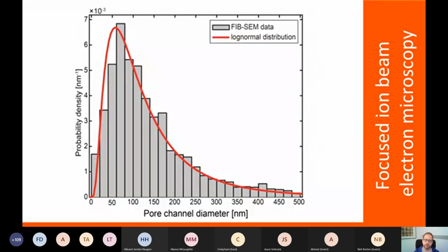So from this, for example, you can get the size of the pores. This here is the pore channel diameter against the probability density to show that in this case, for example, most porosity is about and below 100 nanometers. But it's just one example of many things you can do with this type of 3-dimensional FIB SEM tomography.